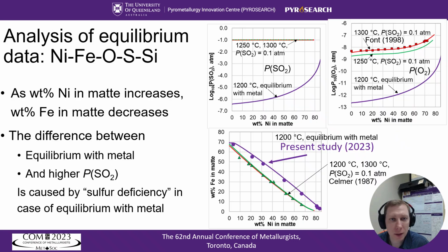On the next 3 slides, we will look at the experimental results compared to literature data and to thermodynamic model predictions. Results of the present study are shown using circles. In these diagrams, the x-axis corresponds to the concentration of nickel in matte, which we are trying to increase during the process by removing iron sulfide. So, on this diagram, the concentration of iron decreases as a function of nickel in matte. The other 2 diagrams show the partial pressure of SO2 or O2 for these conditions.